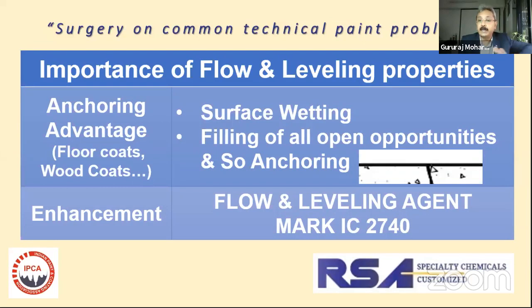And if there is no flow, what will happen is it will not flow into the crack. The paint will be only on the surface. There will be some air entrapped in this. And if the surface is exposed to heat, the air will expand and cause the film separation. This is going to limit the life. So a good flow leveling agent, especially on these surfaces, will add value and improve the quality of your product.